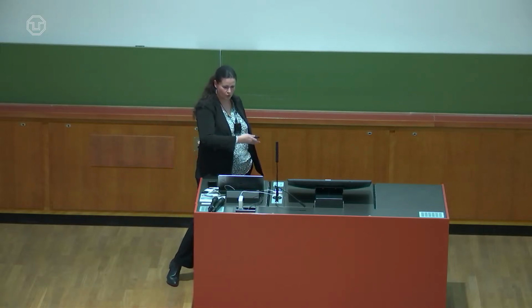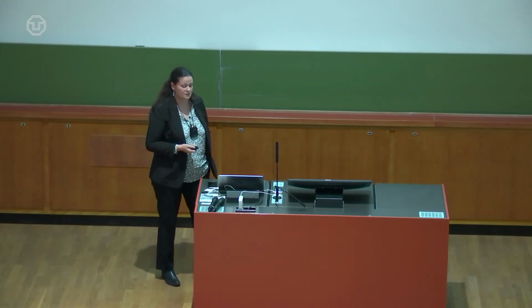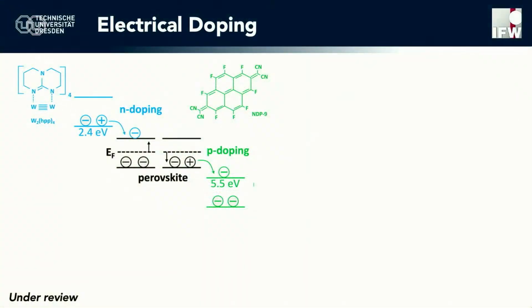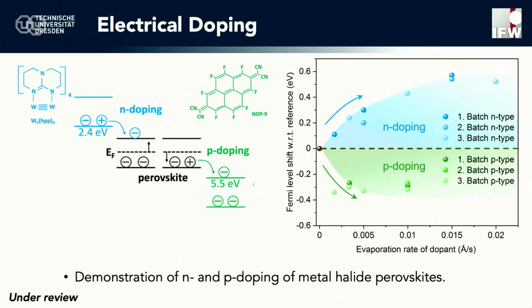An alternative to that would be to co-evaporate the dopants alongside the perovskite precursors all throughout the layer. And this is exactly what we did in our very recent study, where we selected a molecular N dopant and a molecular P dopant, and then we incorporated them into the perovskite by co-evaporation. And you can see here the position of the Fermi level with respect to the undoped reference that clearly shows that as we increase the evaporation rate of our dopant, so we put more and more dopant inside, we can tune the position of the Fermi level.